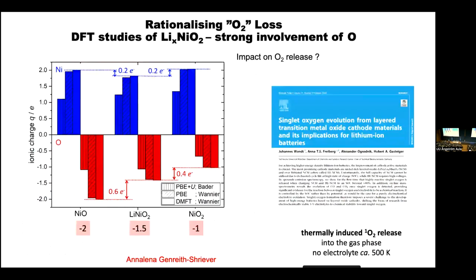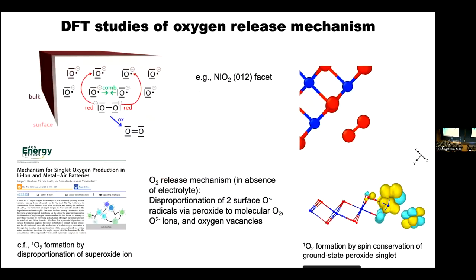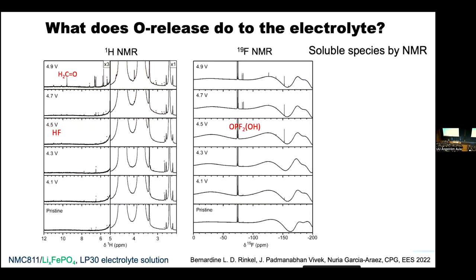So then let's reflect on how the oxygen comes off. Inspired by work of Hubert Gasteiger, who showed that you could get singlet oxygen if you just heat these materials up, she then calculated the mechanism of oxygen release. This little cartoon shown here, where the oxygen comes together, forms a peroxide, and then disproportionates off the structure. It's this coming together to form the peroxide, and then its release, that explains why you get singlet oxygen and not triplet oxygen. Singlet oxygen is the paired state, and so you need to form a singlet peroxide, which is then removed.